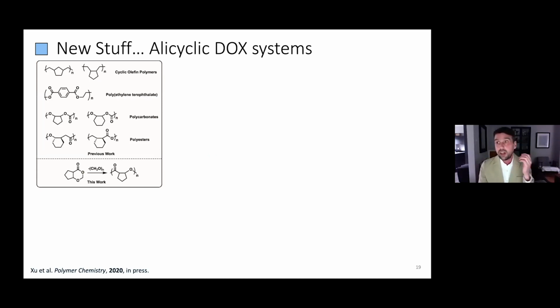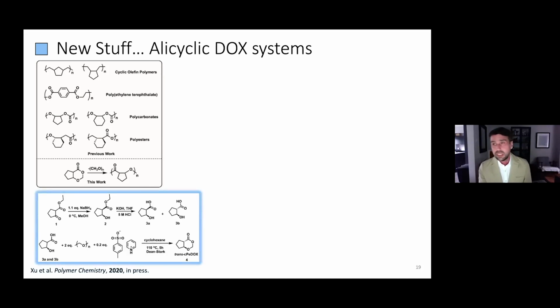We have a strong interest in exploiting this on other systems, so we can perhaps introduce cyclic rings in those. We have a strong interest in using those to control crystallinity and control packing in these polymer-based systems. This becomes a lot less sustainable because our monomer route is much more difficult, but as a proof of concept, we wanted to show that this would work. It's quite complicated to simply get to this derivative. We have worked with the other derivative before, but the trans derivative is the one that actually ring opens.